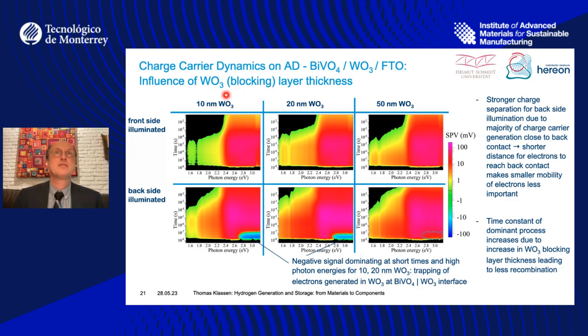And here we have bismuth vanadate together with tungsten oxide on the FTO, and we can see the differences that we get if we increase tungsten oxide and if we illuminate from the backside or from the front side of the coating. And yeah, these diagrams with their color code are difficult to interpret at first glance, but I can tell you that there are certain features that help us understand what's going on in the specimen and which screw we have to turn to improve our coatings even further.